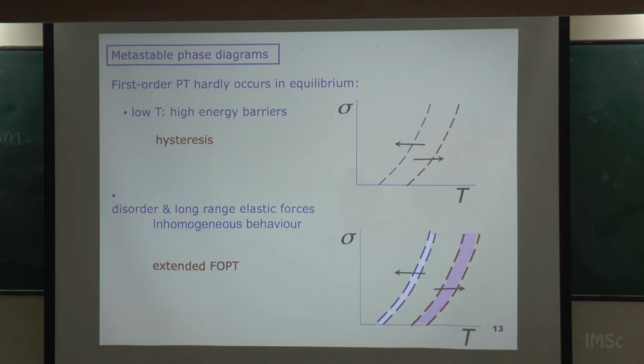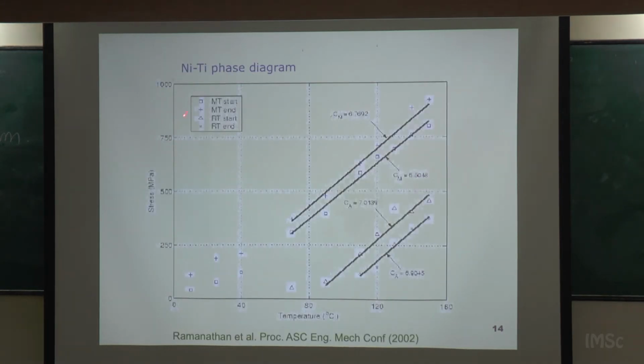It's not on a line, but on a region. And similarly with the other line; the other line also extends. So typically, the phase diagrams of these systems that have first order phase transitions are like this one here. This is a nickel titanium phase diagram. There are two phases, the martensitic phase and the R phase. And instead of giving you where the line is, they give you four lines: the martensitic start, martensitic end, or austenitic start, austenitic end, depending on which direction you go, with a start and an end every time.